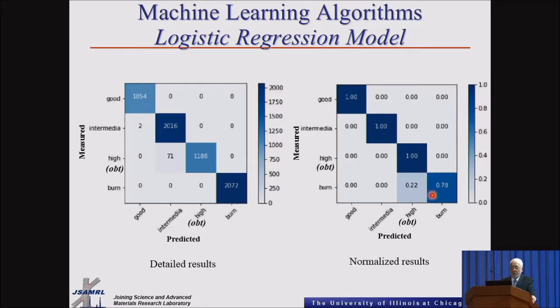The same thing with the logistic regression model. It gives similar results as far as the good, intermediate, and onset of burn through. They were very close to each other in terms of the prediction as well as the measured. And the only problem was again with the burn through.